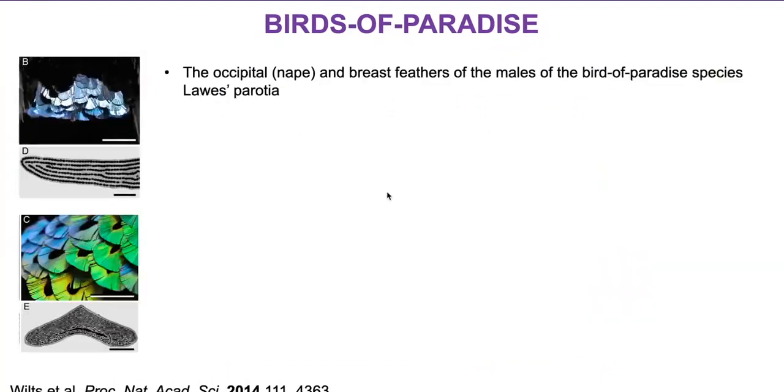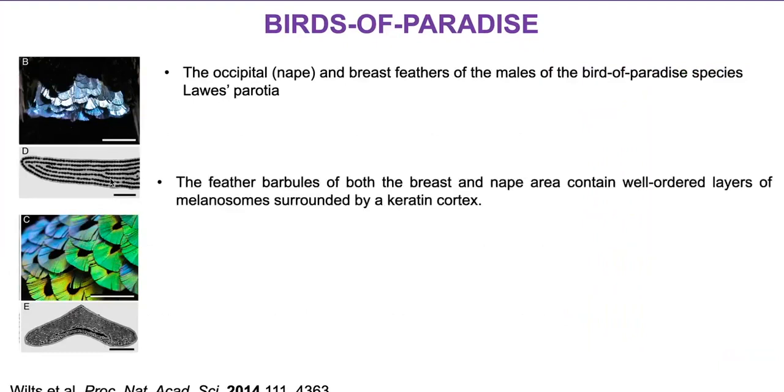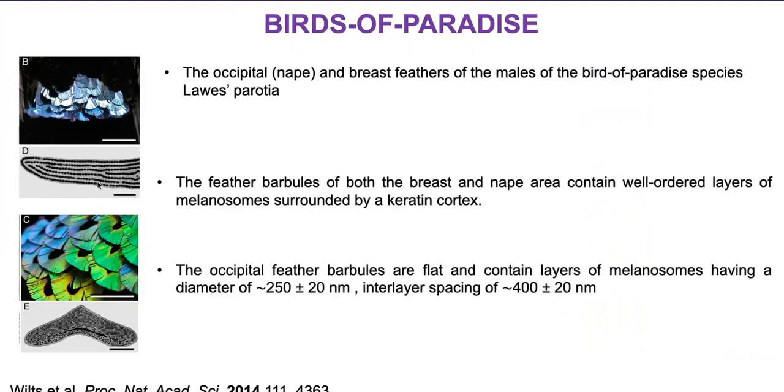And these colors, if you take now the silver-like feathers, and also if you take a look at these greenish shiny colors, you see they are made up of similar materials, or exactly the same melanin, which I discussed, for example, in octopus ink, where there's simply polymer. But here they are arranged into a very well organized structure of certain size. In this case, it's about 250 nanometer, and they form nice two-dimensional layers, and the spacing between the layers is about 400 nanometer.